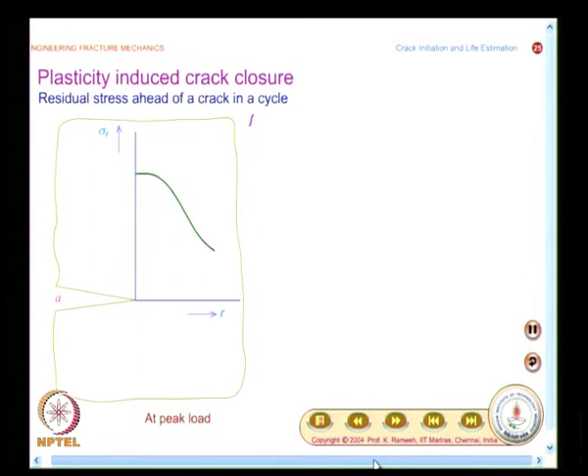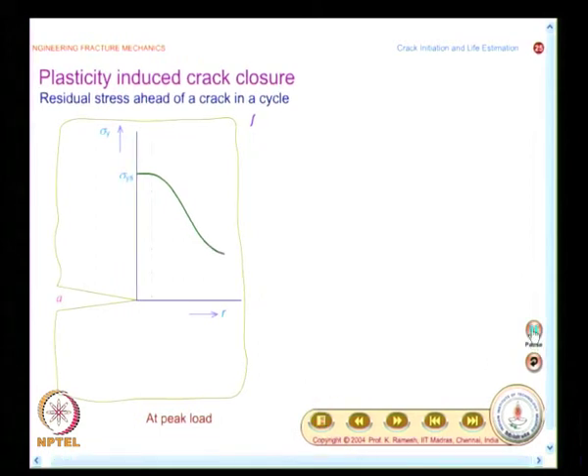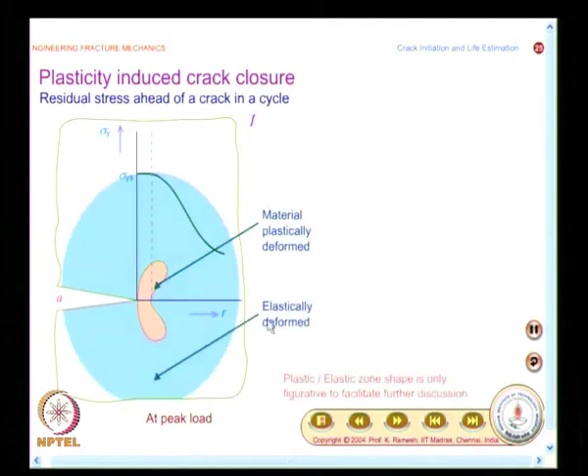and the stress field is shown like this. Along the crack axis, how does the value of sigma y change? It reaches a value of sigma ys, and we all know from the plastic zone modeling what is the shape of the plastic zone. And just to understand the concepts further, I show the elastically deformed material here. So, when I increase the load from 0 to peak load, in the vicinity of the crack you have a plastic zone developed, which is surrounded by elastic material.